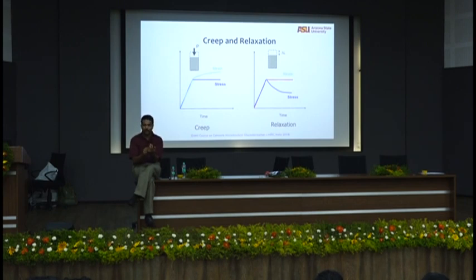Great, high strength concrete, wonderful. Look at the chances of cracking in those concretes, right? This is common in the US with very high strength bridge decks that they do. So high strength, high performance bridge decks. When you have high performance bridge decks, you invariably have cracking because higher strength concrete does not relax well enough. Stresses don't relax. This is like somebody who will not cry, keeps holding on to stress, and finally when they break, they just break down completely. So you have very high stress, can't relax, they fail.